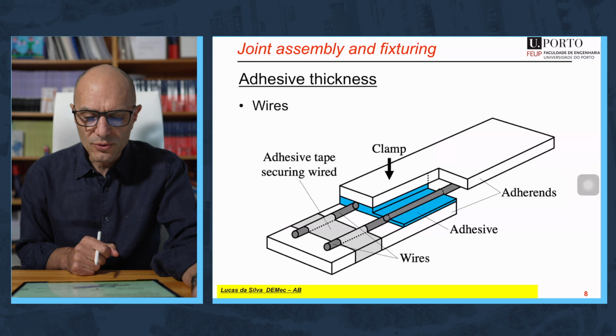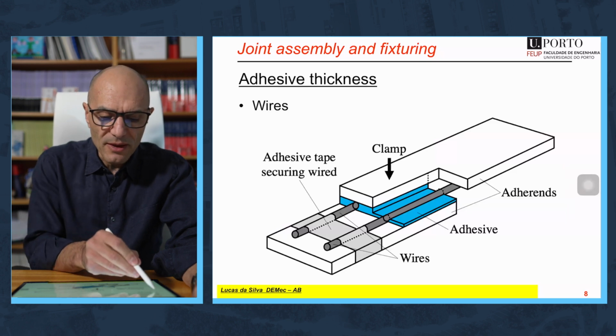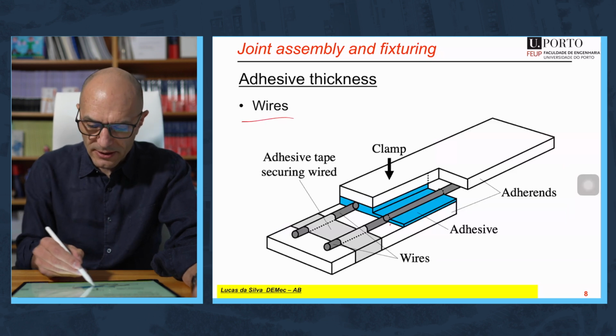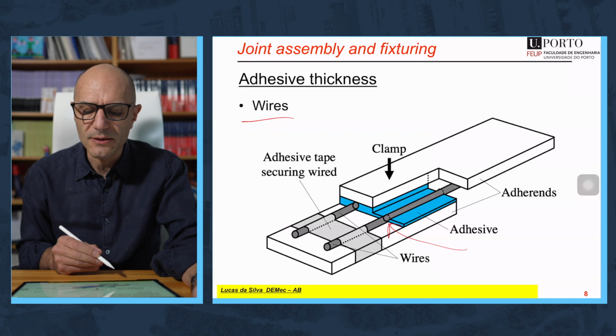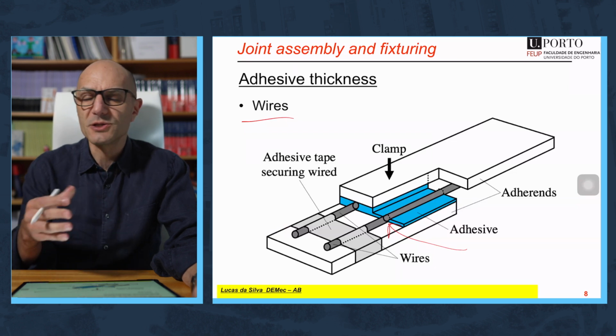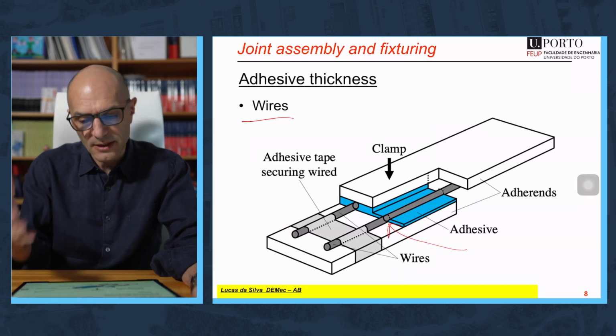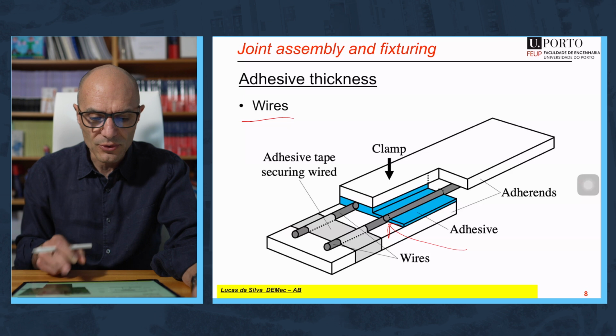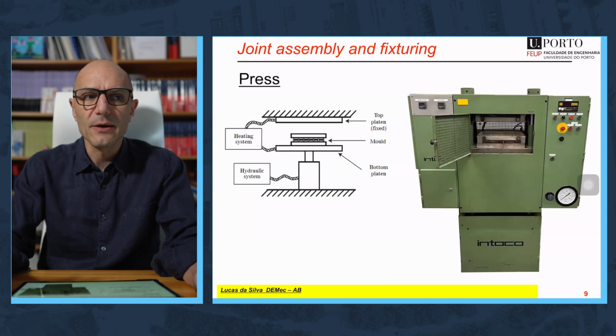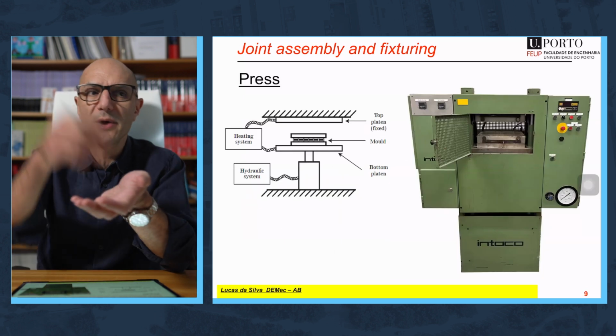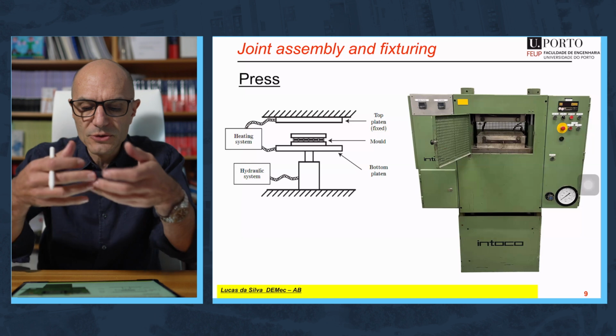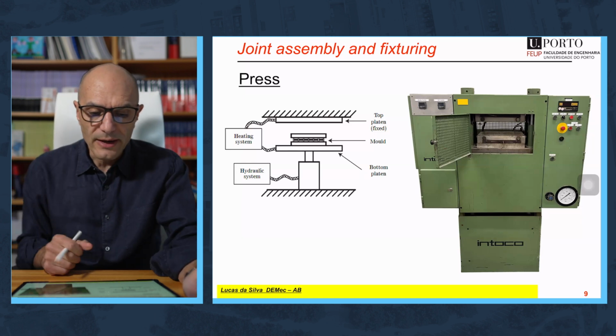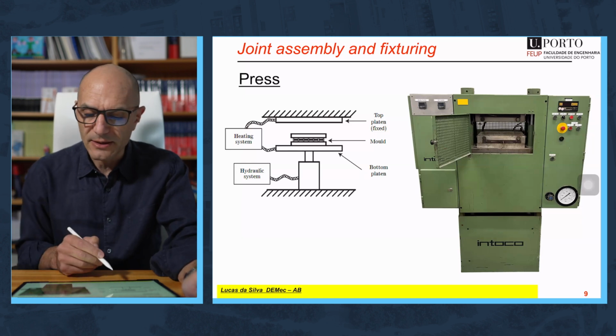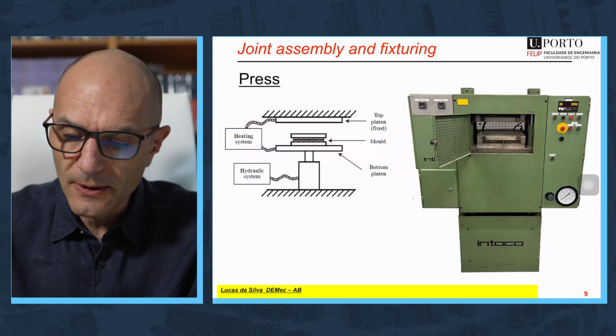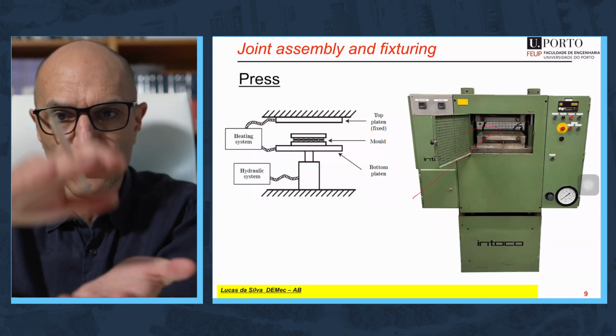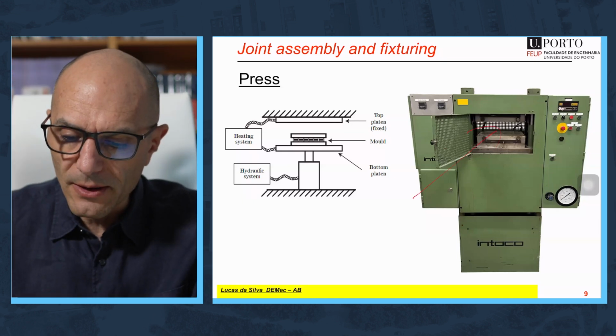Another way to control the thickness is to use thin wires. Here in this figure it's exaggerated, the thickness of the wire. Generally you don't even see it. This is another good way to control the adhesive thickness. To apply pressure, you can use weights. You can use also something more controlled, like a press, like indicated here. So you put your mold in here and then you apply pressure in the press.